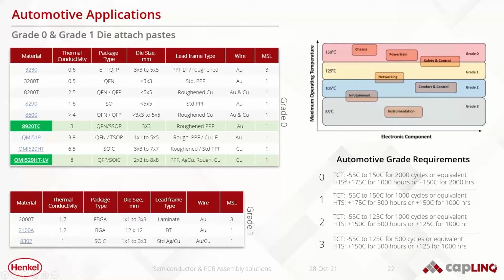Most stringent means a temperature cycling of -55 to 150 C for 2000 cycles or the equivalent. If you take a look at the materials that we have available for the grade 0, you'll notice that these are all lead frame type applications. It's no surprise then also that these will also give you the highest level of MSL reliability. There's two products in particular that I will highlight after this slide. There are materials, however, that if your requirements are only for a grade 1 automotive application, then there are other materials that may be available even for package types that aren't a lead frame, like BT or a laminate substrate.